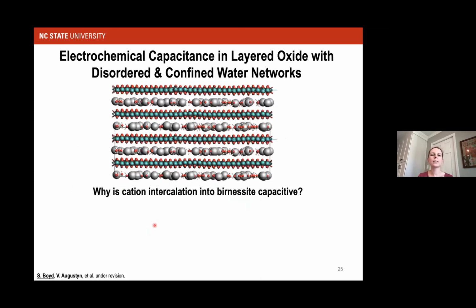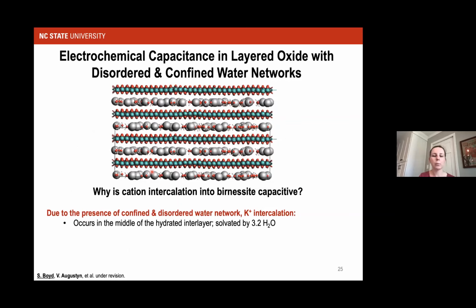So why is this cation intercalation? Why does it appear capacitive? And here's kind of a big picture of many layers now with the water in between. We think that the presence of the water network here is very, very critical. The potassium ions that are intercalated end up having about half of their solvation now in the interlayer by these structural water molecules.